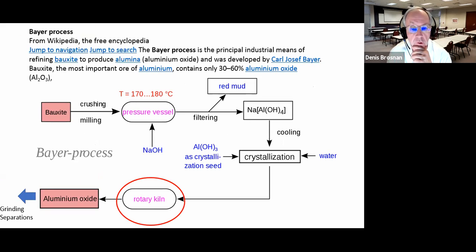If you don't know about the Bayer process, you can look up Wikipedia, which I give full credit to, and of course, the Bayer process is a caustic digestion of aluminum oxide. Caustic soda is added, sodium carbonate, or sodium oxide, rather, sodium hydroxide. I'll get this right. Then that's going to remove some of the aluminum oxide into a liquid phase, leaving a red mud residue because of the iron. Then we can crystallize out the aluminum oxide as aluminum trihydrate. And we can take that trihydrate, briquette it, run it through a rotary kiln. And if it's super high calcined, we'll make tabular alumina. If it's lower temperature calcined, it'll be calcined alumina as our raw materials.